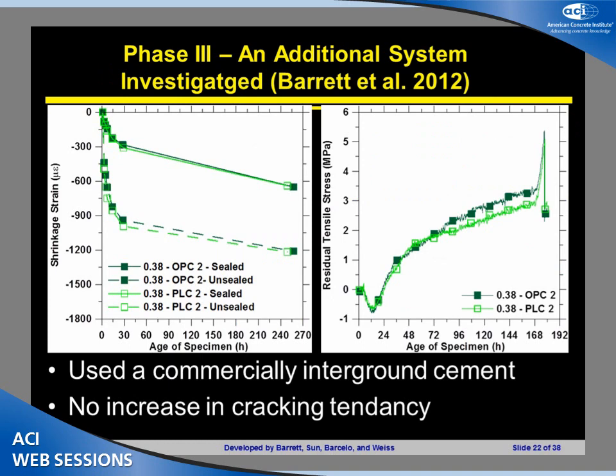Third phase of this is, again, just to look at a different binder. And again, I want to point this out because this is a different binder, 0.38 water to cement ratio. Sealed shrinkage up here. The green and light green lines, and I don't know why we did green and light green, I guess that was to stay green with the theme. But these are the drying. This is drying down here. These are the sealed shrinkages, and you're hard-pressed to see a difference between those lines.